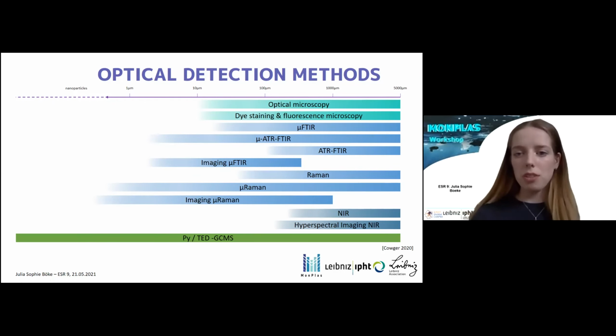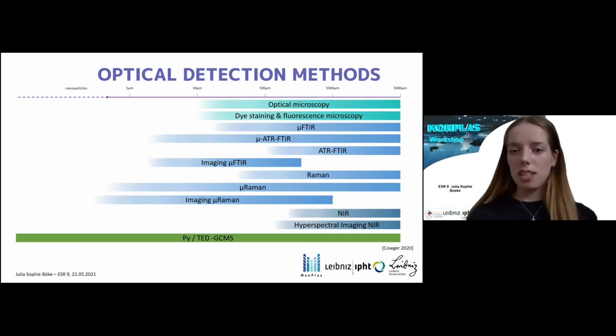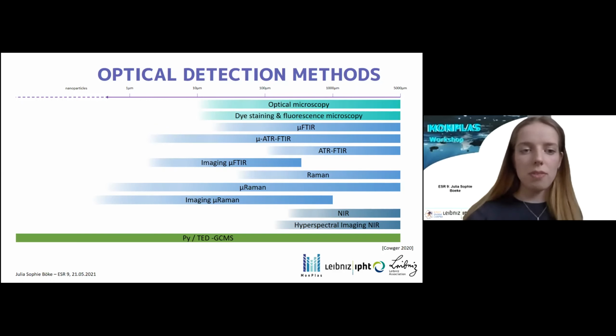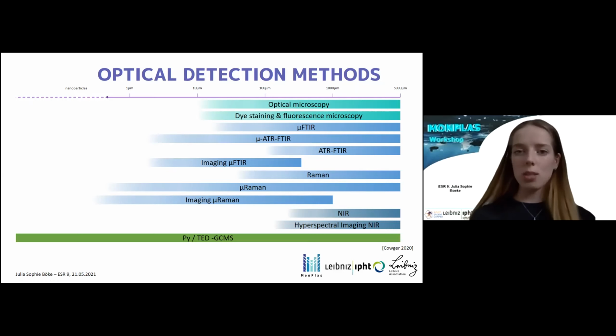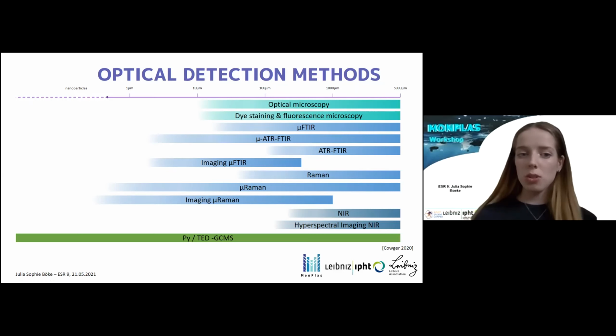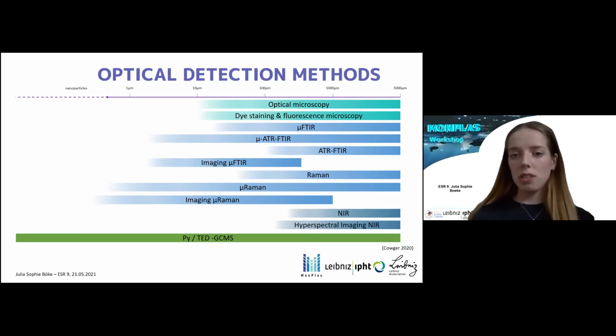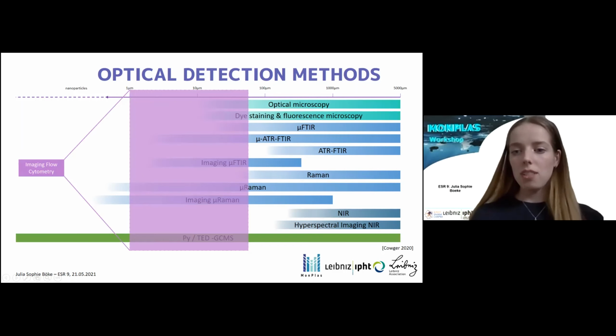However, when we look at what we want to measure, we also have to take into consideration the technique we want to measure it with to make sure that we don't get biased. Because microplastics tend to get smaller and smaller over time, and recently we also discovered that there are not only microplastics, but also nanoplastic particles. The method that we use to detect these particles can be largely dominated by either small particles or many particles at all. So we have to choose the method carefully. During these next few minutes, I would like to introduce you to a combination of optical detection methods.